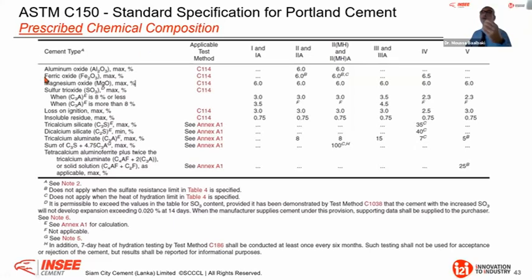Okay, now Fe2O3 iron, you have also 6% maximum, and the BC is said here clearly that it does not apply when sulfate resistance limit or when heat of hydration limit are specified. And this is the performance base, I will come later to it. Therefore, you do not have to fulfill this requirement if you make a performance based test. Okay, now magnesium oxide, therefore you have limitation 6%, it will be 5 for European for SLSI. This is for magnesium oxide.